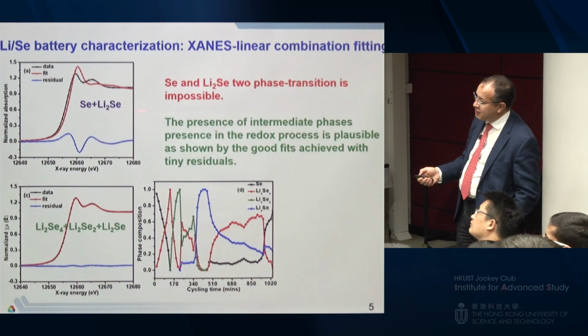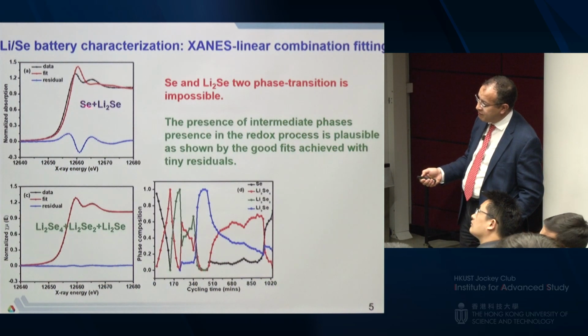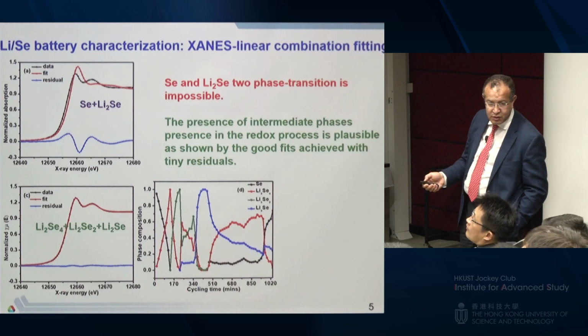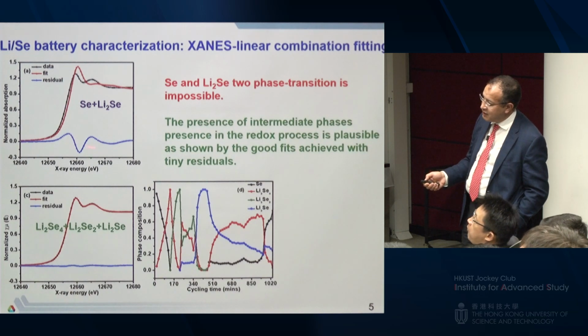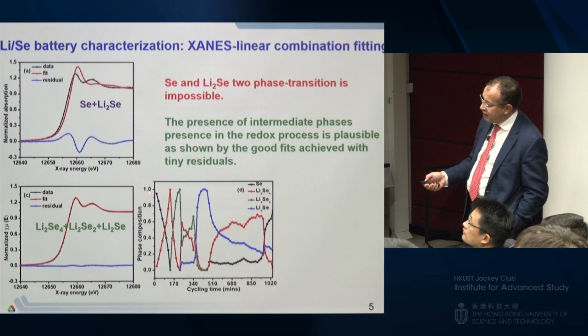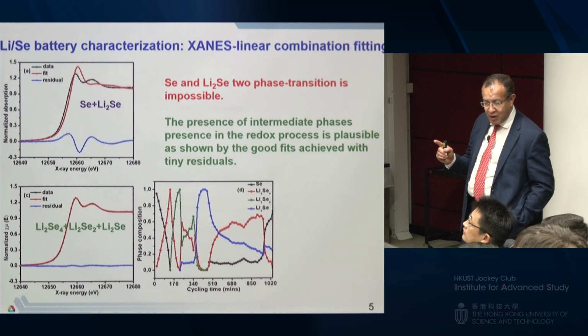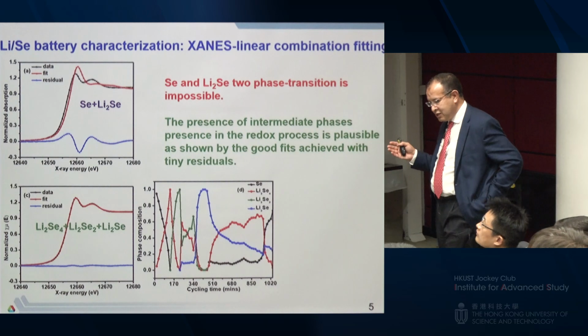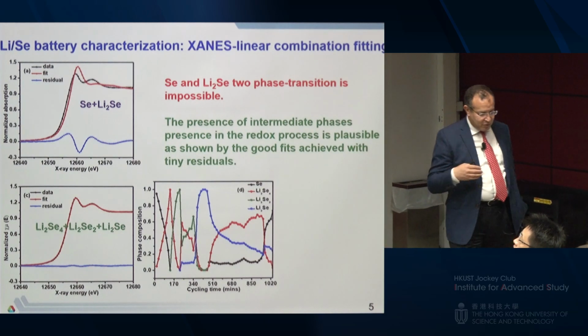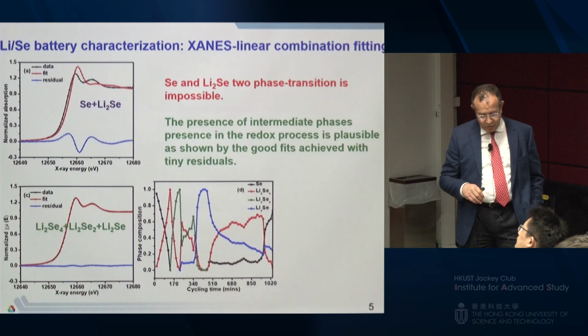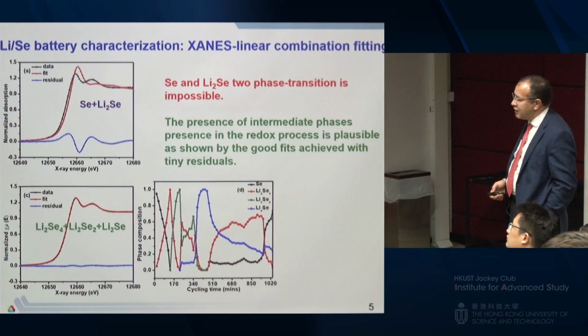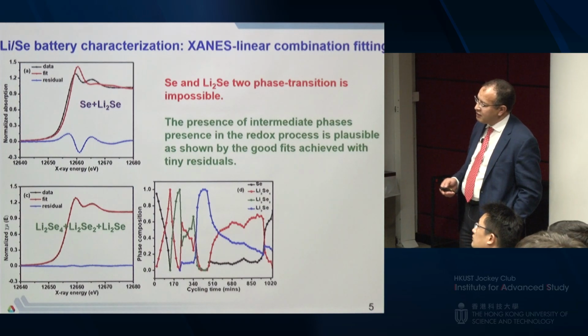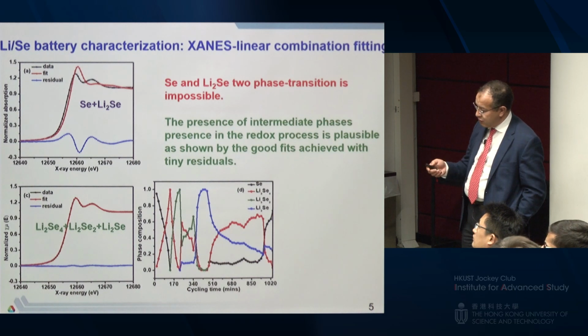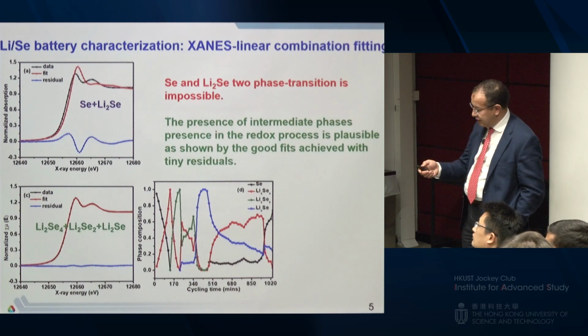So when you try to fit it with two phases without any dissolution, it doesn't fit well, obviously. But when you add the polyselenide, it fits very well. Then you have a program to tell you at what time a phase is starting and when it disappears, for instance. So that's a problem. We were very disappointed because we were able to improve the performance by putting a high excess of the active material, but there is a dissolution, and therefore your capacity failed eventually.